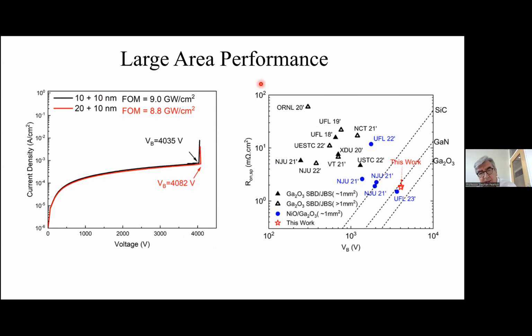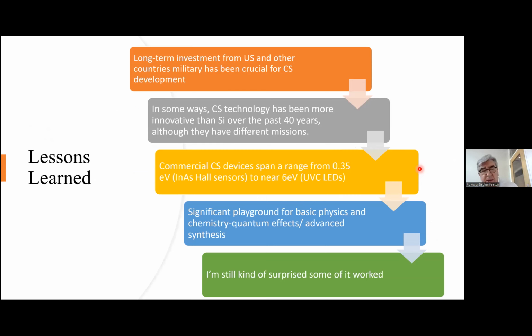progress. And for large area devices, so we'll take devices 1 millimeter squared or larger, that would be used for high current applications, there again, we can show that even with a large area device, you can get 4 kilovolts and you can get 4 amps. I've seen results up to 15 amps. So you're starting to get not just a high voltage, but also a high current capability as well. And again, if you go back 3 or 4 years, the performance of the devices reported in the literature was well short of the theoretical capabilities. But with time, you can see now that there are results that are close to the theoretical maximum for gallium oxide. So what can we conclude from all of this?